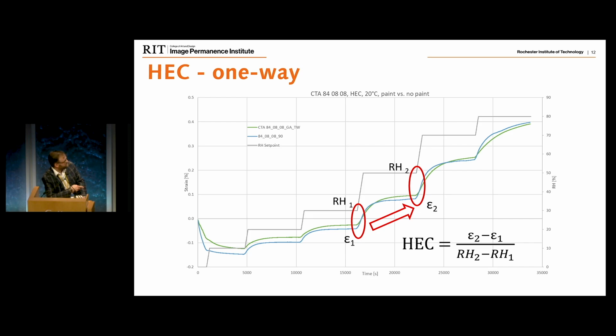So what you see here is the 90-minute period, and then the strain curve of the sample as it goes through the humidification process. As you can see here, this is why we're avoiding the 80%. You see here that the sample was stabilizing, and then it started softening and deforming plastically. We found out that above 75-ish%, depending on the polymer composition, we're starting to get plastic deformation instead of elastic. So that's where we're dropping the 80% from the two-way tests.